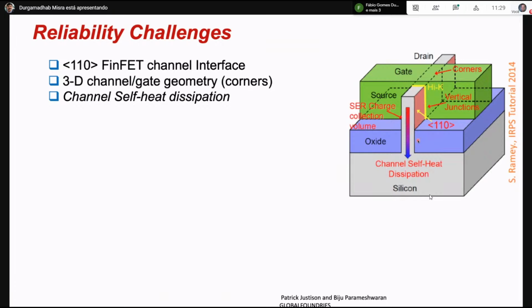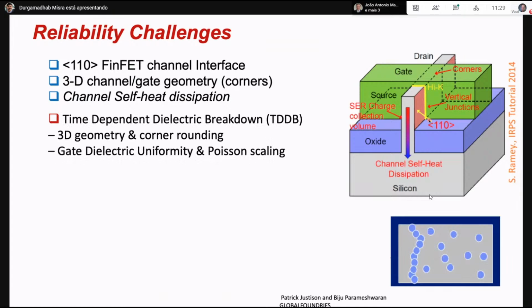There is some sort of change in the corners. And then we have breakdown, because even though the voltage scaling has been done, there is still a possibility, because of the corner rounding and all these things, that it creates issues in non-uniformity of dielectric around the corner. So that creates additional trouble of dielectric breakdown.